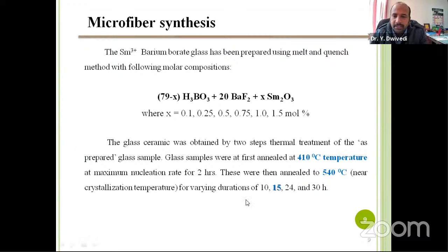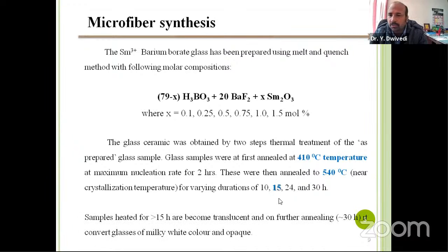We heat it for different hours, for example 10, 15, 24, 30 hours, even less. We start actually from 5 hours, but we optimized that if we heat it beyond 15 hours, the glass becomes translucent, and at 30 hours it's completely opaque, due to the formation of big size crystals in it.